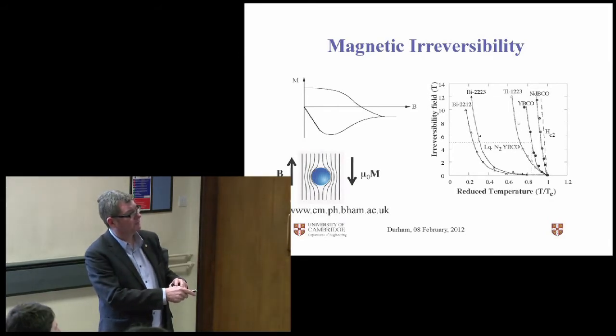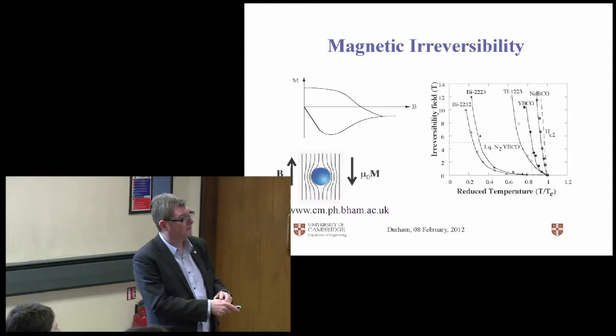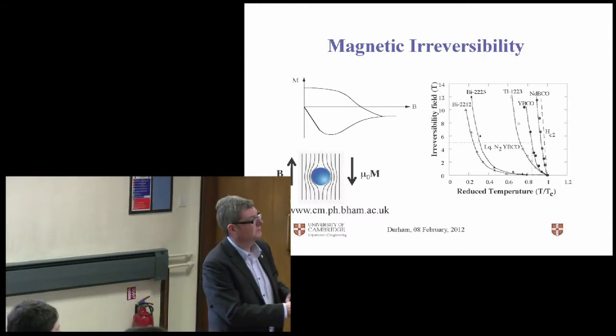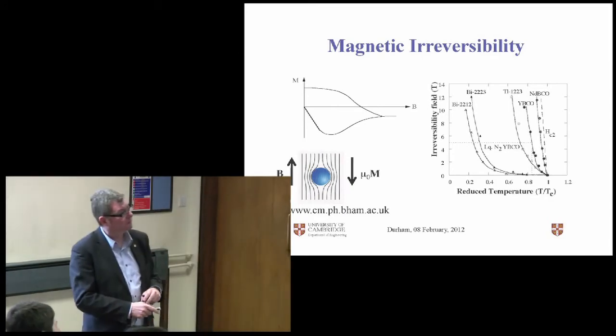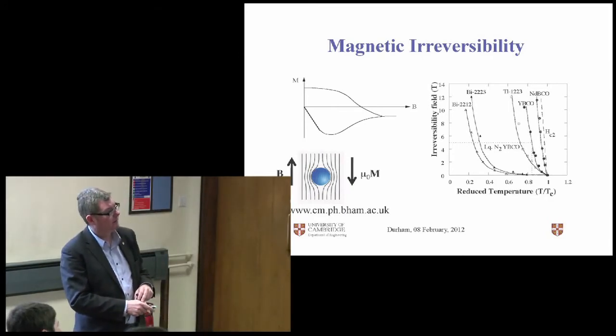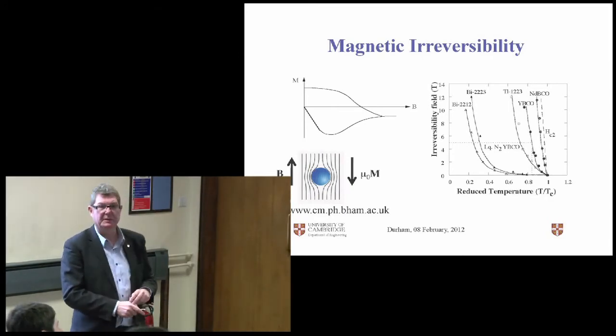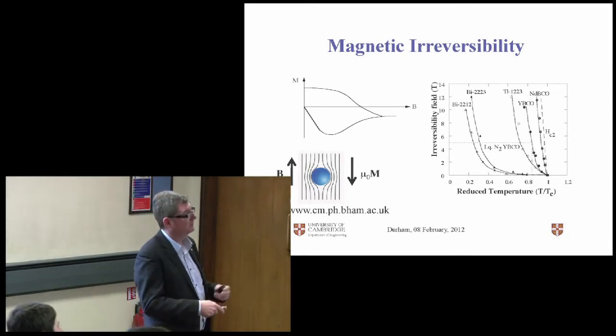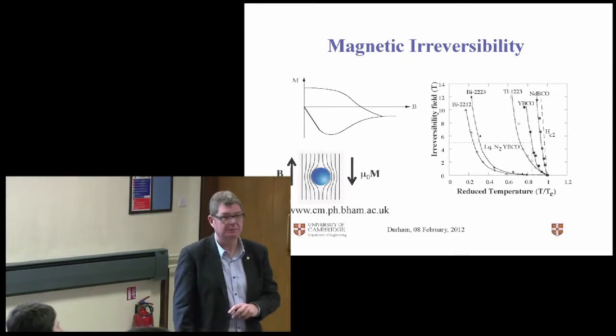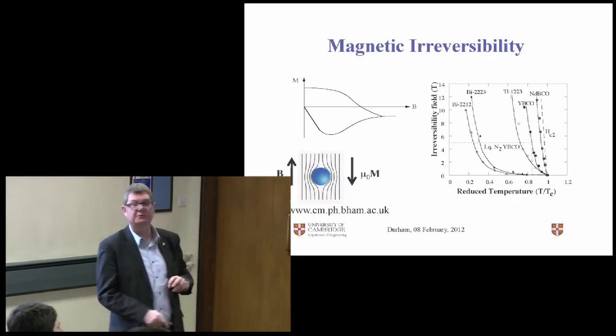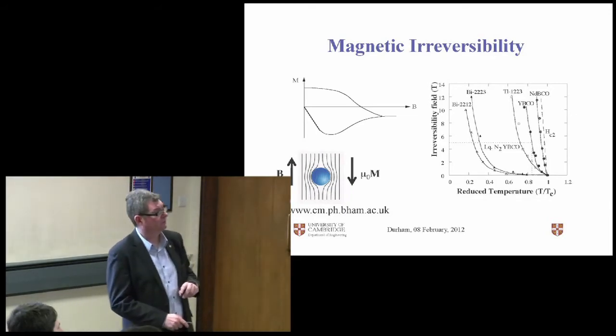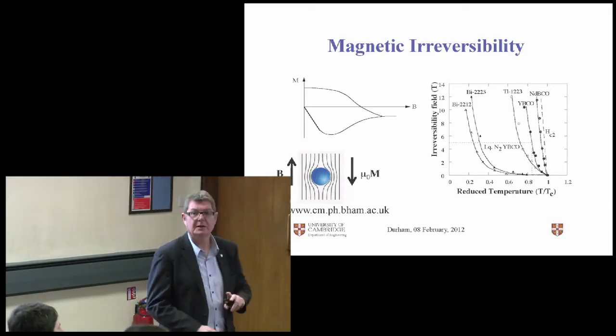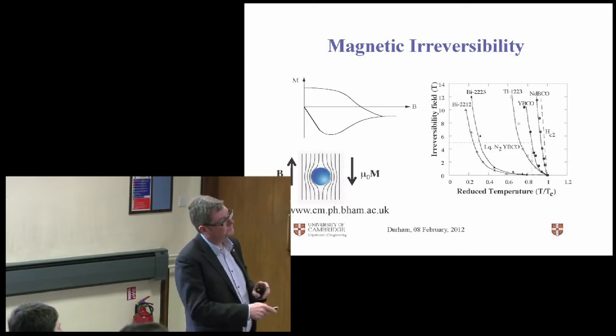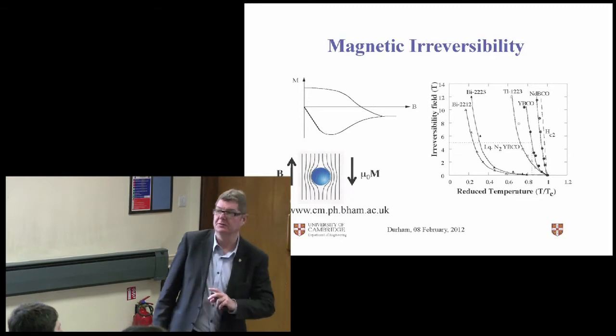It's a reduced temperature scale, which is a slight inconvenience, but if we read up and across at 77 Kelvin, for the bismuth-based materials, we see we get a very small magnetic field. There's no way at 77 Kelvin we can use the bismuth-based materials to generate large fields, whereas at YBCO, we read up and across, we get a field of about 5 Tesla. And that's significantly bigger than anything we can do with permanent magnets. So that tells us that the rare earth-bearing cuprates have got the most potential for applying these materials at high field.